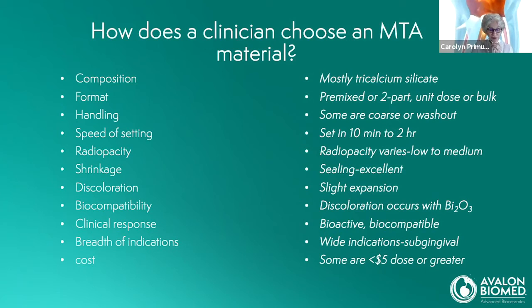If you avoid materials that contain bismuth oxide, you'll avoid discoloration of the tooth over time. All these MTA-based materials are bioactive, they're biocompatible, and the clinical response is excellent. I haven't read any clinical trials that show that one material has a superior clinical response over time in humans over others. The indications vary widely, but please note that they are used subgingivally or intracoronally. They're not suitable for long-term use as a restorative.